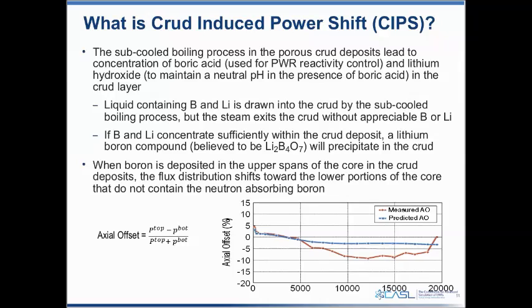In PWRs, we have a term called axial offset, which is a very gross measure of the axial power distribution. It's defined as the power in the top half of the core minus the power in the bottom half of the core, divided by the total core power. Pressurized water reactors operate with a negative moderator temperature coefficient, so the cooler, lower temperature zones tend to be a little bit more reactive, and as a result, axial offset in a PWR is typically slightly negative throughout the life of the cycle design.